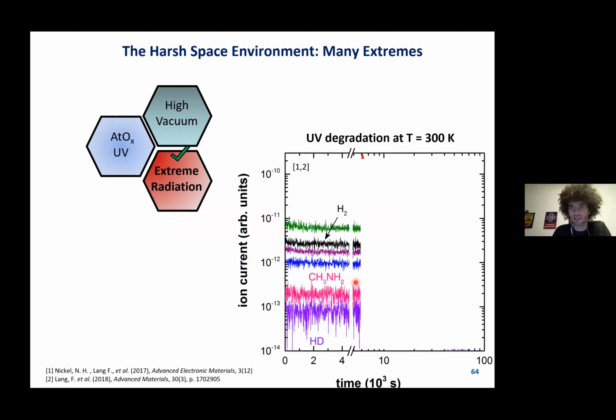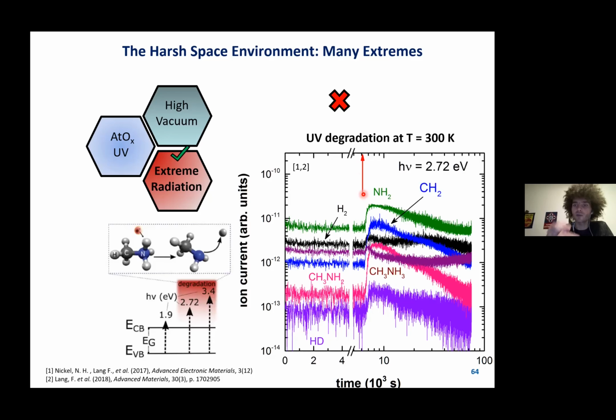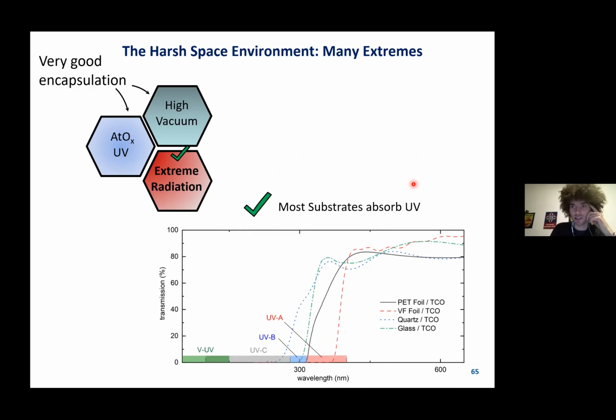And you can see this quite nicely, for example, when you look at the UV degradation of just a bare MAPI perovskite film. What I'm doing here is I have a mass spectrometer behind a perovskite film in high vacuum. And once you shine light here, you can see the effusion of methylamine, hydrogen, NH, etc. So the perovskite is decomposing upon the UV. This is a problem for any space application. So we will need a very good encapsulation.